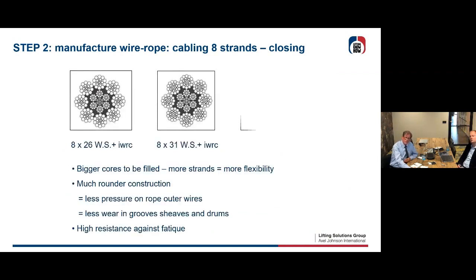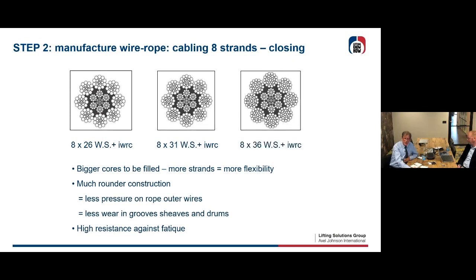If you use 8 strands to do the closing, then you have a much rounder steel wire rope. Like presented here, you can have 8 times 26 Warrington seale, 31 Warrington seale, 8 times 36 Warrington seale, and so on. Notice that you need to have a bigger and flexible inner core, and with 8 strands, you're going to have lower pressure because you have more surface in contact with the grooves of sheaves and of drums. So there's going to be less pressure on your rope outer wires. That means you're going to have less wear on your sheaves, drums, and wires.